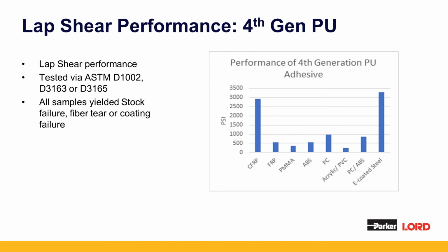Lap shear performance. So this just shows some general performance on a variety of materials of this newest 4th generation structural polyurethane from Parker Lord. We've measured the shear strength via the typical methods of ASTM D1002, 3163, and 3165, depending on the material used. Although the strengths in the center are much lower, it should be noted that we saw stock failure, fiber tear, or coating failure, some of the best performance achievable by an adhesive on all the different materials.